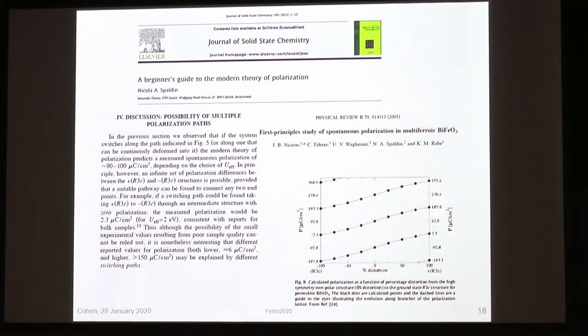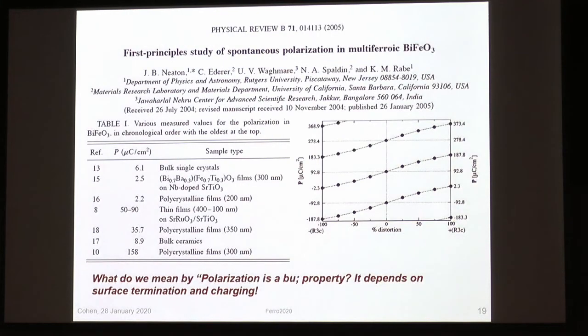But if you look at the literature, the actual polarization values that are measured with bismuth ferrite are kind of all over the map. And they mostly, for bulk crystals, don't agree with this. They agree with a difference where you took this small value of polarization and subtracted zero from it, as opposed to this large number that has this half a quantum in it. So here's some of the experimental numbers for bulk single crystals. You see the polarization is 6 microcoulombs per centimeter squared. And for thin films, it's been measured up to 90. And that's more consistent with the number that they're getting. And sorry about the typo here.